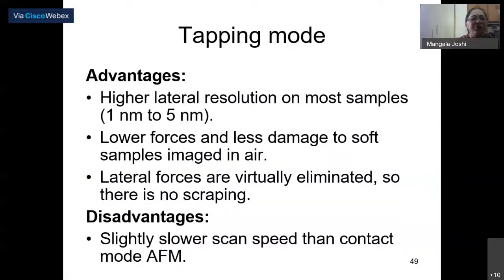So in the tapping mode, the advantages that you are having are high lateral resolution on most samples, lower forces and less damage to the soft sample, and lateral forces are virtually eliminated. So there is no scraping. Disadvantage is it is slightly slower scan speed than the contact mode AFM. So next slide.